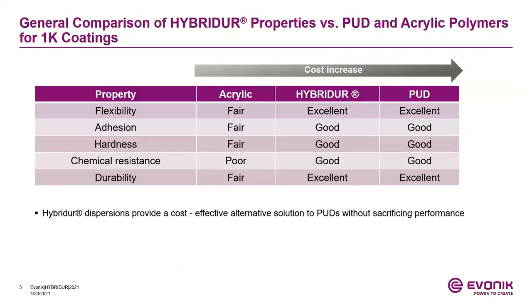We demonstrate this further, comparing Hybridur properties versus polyurethane dispersions and acrylic polymers. So in terms of flexibility, adhesion, hardness, chemical resistance, and durability, Hybridurs are comparable to conventional polyurethane dispersions. The biggest advantage of the Hybridurs is that polyurethane dispersions are very expensive, very high in cost. And acrylics, even though they are low in cost, do not provide the same performance properties compared to the polyurethane dispersions, but the Hybridurs fall right in there. It does provide all the performance properties of the polyurethane dispersion at a much lower cost. So the Hybridur polymer dispersion provides a cost-effective alternate solution to polyurethane dispersions without sacrificing performance.